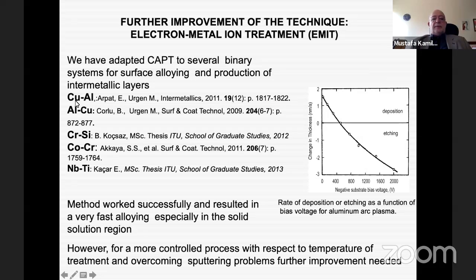We tried to modify copper surfaces by alloying them with aluminum. We tried to modify aluminum surfaces with copper. Chromium silicide, we tried to form cobalt chrome, as I have already mentioned. We tried to alloy niobium with titanium, for superconductor materials. The method worked successfully, though. We can manage a very fast alloying, especially when we work in the solution region.